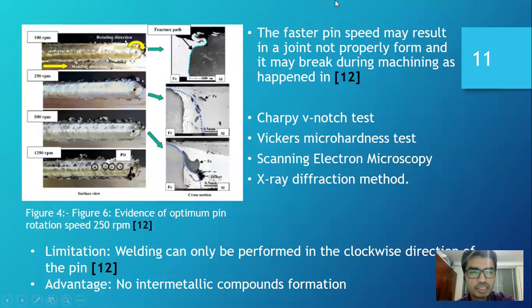So the research followed by Watanabe shows that the pin rotation speed of 250 RPM resulted in the optimum weld strength of the joint. So I'll be using different pin speeds such as 100 RPM, 250 RPM, 500 RPM, 1250 RPM, and will analyze which pin speed is much better to create a high strength of weld for my research design. And it has also been seen that if we use higher pin rotation speed, it will not create a better joint and it may break during machining, as has already happened in Watanabe's research.